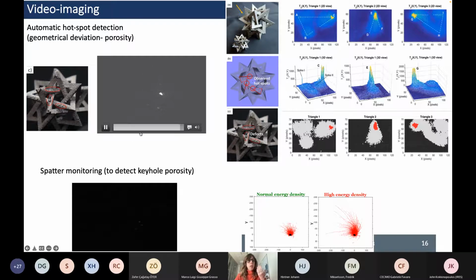So in video, thanks to some sort of in situ and inline imaging and video imaging of the frames you are producing, you can detect in situ and inline a hot spot that at the end is going to result in a defect, or even look at, let's say, the melting products that are coming out from the melt pool. In this study, we have been playing with spatter.